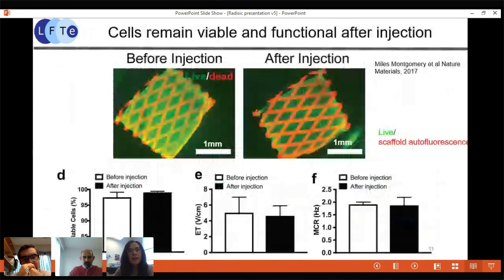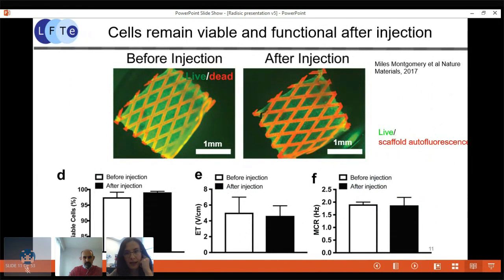And so you can see what this looks like before and after injection. POMAC exhibits autofluorescence that is rather strong in the green and red channels. And to us, that's actually an advantage because we can visualize the scaffold very easily. And you can see here that there is live tissue around this POMAC lattice. And this tissue is alive both before and after injection, as evidenced by a very strong green color.